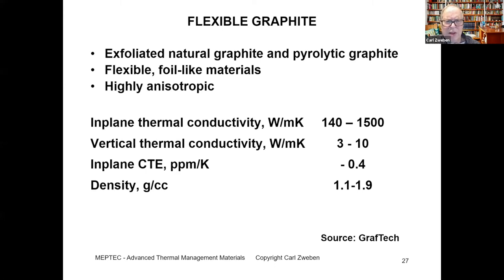And if we look at CTEs, these materials actually have negative coefficients of expansion. That's not a mistake. One of the characteristics of carbon is that in some forms it has negative coefficients of thermal expansion, at least in the in-plane direction. In the vertical or through thickness direction, the CTEs are positive. And the densities you'll notice are much lower than aluminum. Aluminum is 2.7, and we have densities ranging from 1.1 to 1.9.